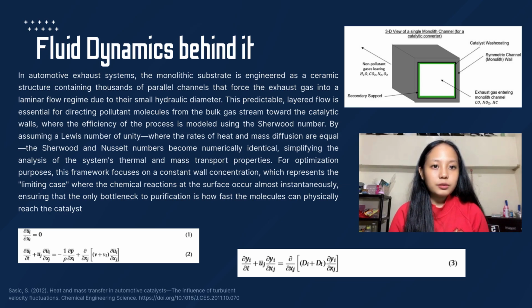Now, we're going to talk about the fluid dynamics behind it. As you can see on the slide, equation 1 and equation 2 are the Navier-Stokes equations, and equation 3 is the species transport equation. So we use the Navier-Stokes equations to map out gas velocity and pressure, but we also need to track the pollutants themselves using the species transport equation. We're looking at how molecules like CO and NOx are pushed along by the flow and how they diffuse toward the washcoat. To keep the math elegant, we use a Lewis number of unity, where heat and mass diffuse at the same rate. This makes our transport constants, the Sherwood and Nusselt numbers, numerically identical, greatly simplifying our thermal and mass analysis.